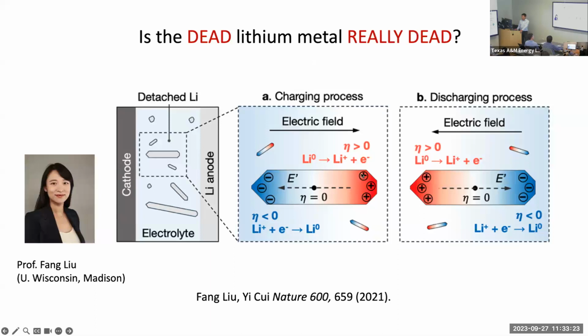So what happens is you polarize the right hand side with positive charge and the left hand side with negative charge. Once you have positive charge here, you dissolve the lithium atom to generate a lithium ion, and the electron moves to the left. The electron picks up the lithium ion and deposits it as metallic lithium, lithium zero. So the right hand side dissolves away, and the left hand side deposits. It's a self-dissolution, self-deposition.